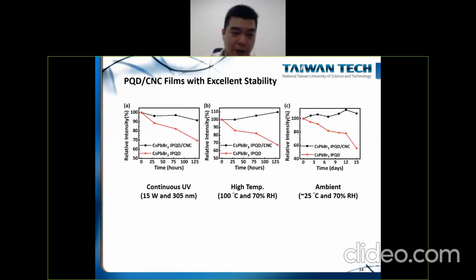For this hybrid film, we evaluate this green emission CsPbBr3 PQD hybrid film, and we compare with the traditional PQD film spin coated on the glass substrate. You can see that under continuous UV, under high temperature, and under ambient condition, it all exhibits superior stability compared with the traditional PQD. So this is a brief.